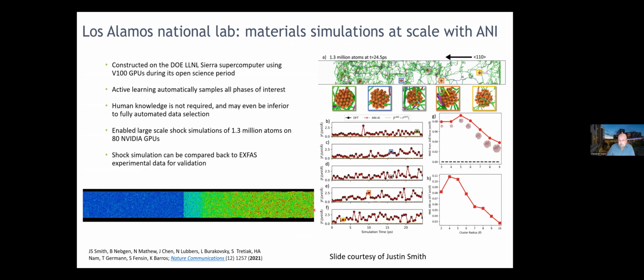So when we induce the shock wave and see the phase transition inside the aluminum, how the shock wave essentially propagates, and look for some interesting clustering of the atoms, what the mechanisms are, all of that. And therefore, that particular architecture is not only applicable for molecules, but can be extended for materials as well. And overall, as the Department of Energy lab, they've done a lot of development for machine learning potentials, especially for f elements.